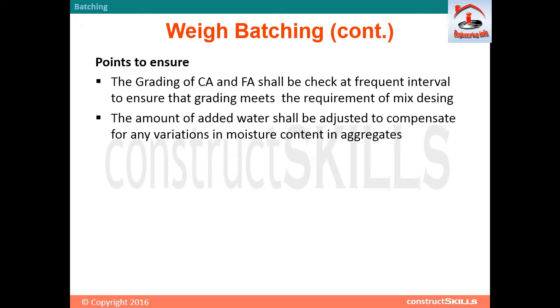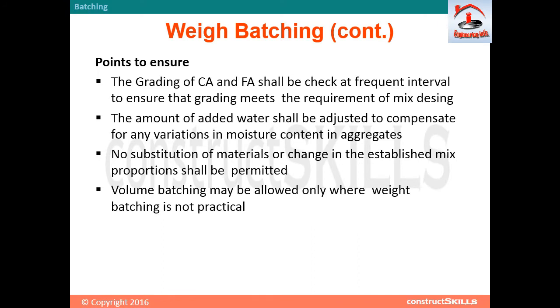Points to ensure quality: the grading of coarse aggregate and fine aggregate shall be checked at frequent intervals to ensure that grading meets the requirement of the mix design. The amount of added water shall be adjusted to compensate for any variations in moisture content in aggregates. No substitution of materials or change in established mix proportions shall be permitted. Volume batching may be allowed only where weight batching is not practical.